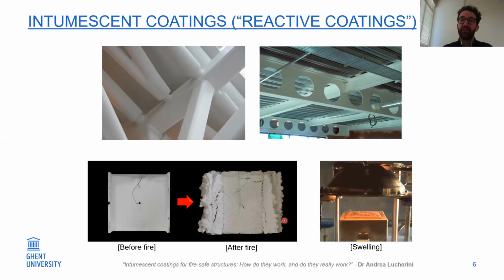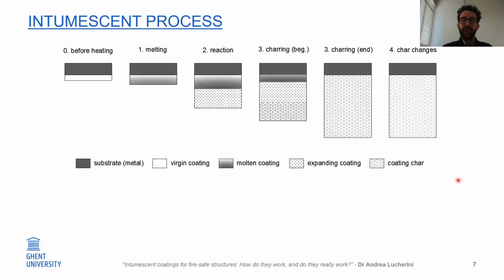And this is an example of a calorimeter test. It's a paint exposed to heat, and you can see how the coating swells. Intumescent coatings are usually called that, and they're specific because they are characterized by the Intumescent process. On the left, you can see before heating. Imagine a steel plate coated with Intumescent coating. This is the virgin coating.